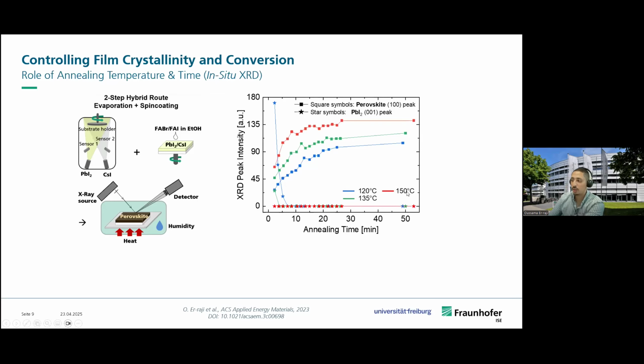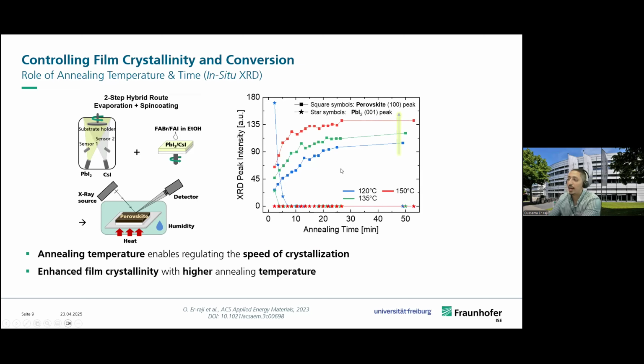When we now go to 150 degrees, we observe that the reaction is even faster. Only 2 minutes are enough to have a full conversion of the lead iodide phase, and again a similar pattern for the perovskite peak. So this really shows us that annealing temperature can play a role in regulating the speed of crystallization. The second thing that we can see is that the higher the annealing temperature, the higher the stabilized value of the perovskite peak. So this also shows us that the annealing temperature can play a role in regulating the film crystallinity of our perovskite.